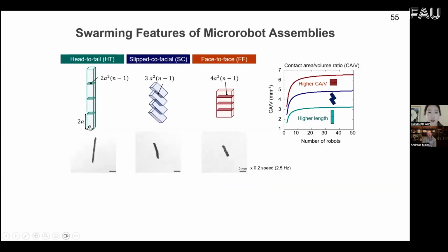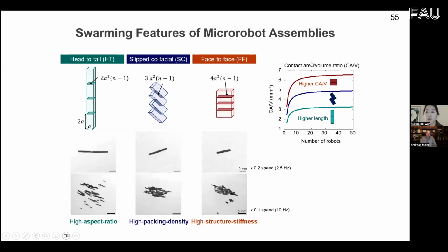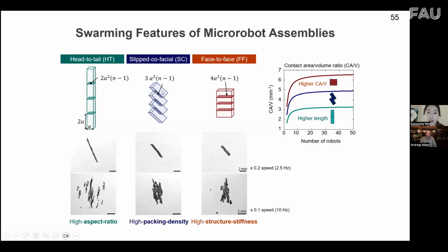The reason why we program this magnetization profile is that each assembly has different preferred functions for the swarm behavior. The first one is head-to-tail assembly of the microrobots, which has the highest assembly length. On the other hand, the face-to-face assembly of the microrobots shows the highest contact area to volume ratio, which makes the highest structural stiffness during their swarming behavior. And this slip co-facial assembly of the multiple robots results in interconnection points through the magnetic attraction, and it makes the highest packing density of the swarm behavior.